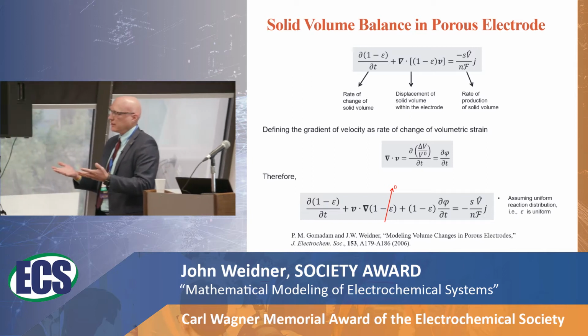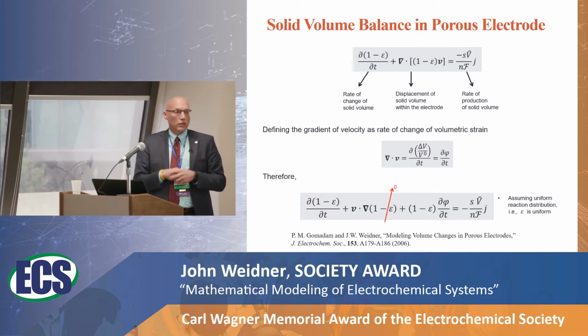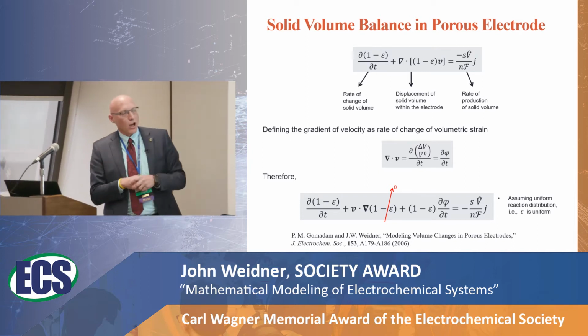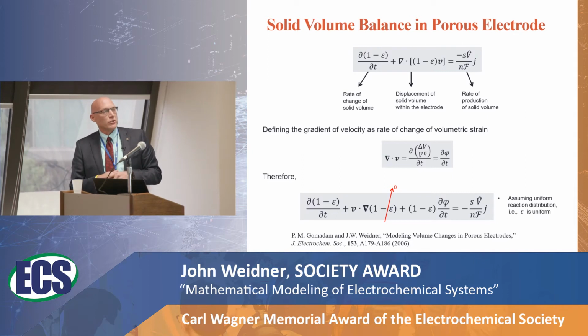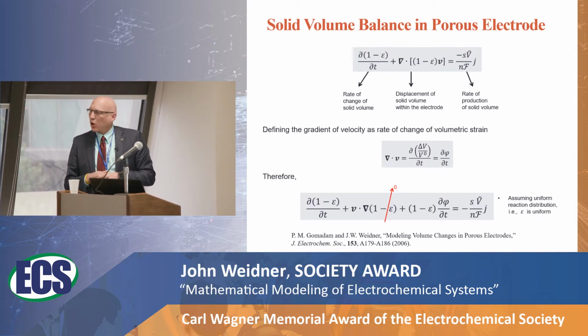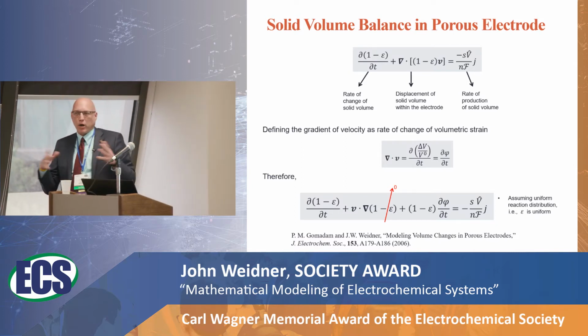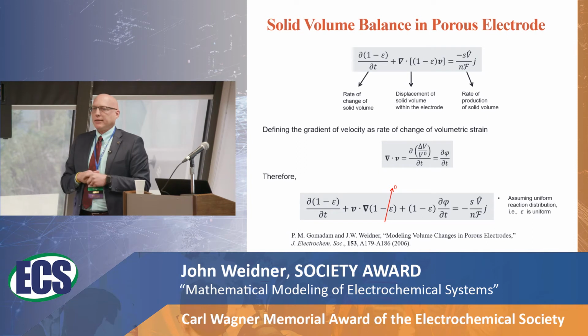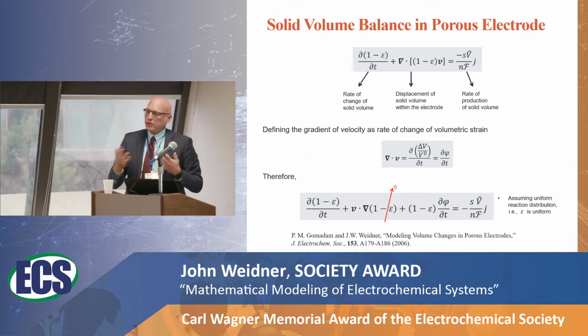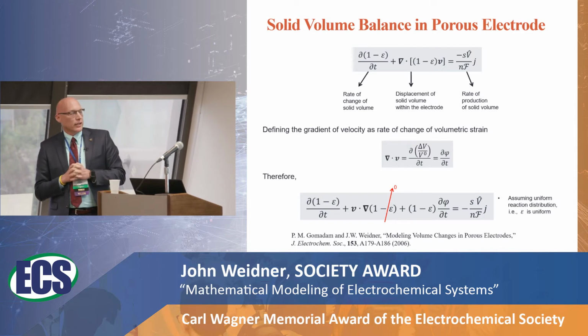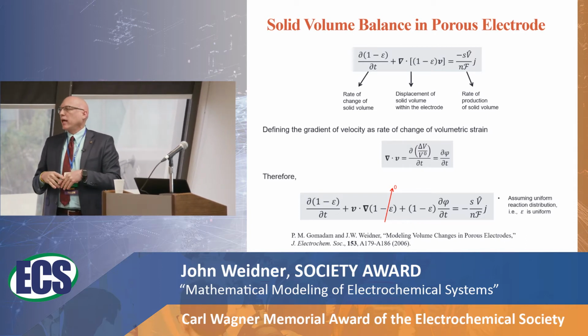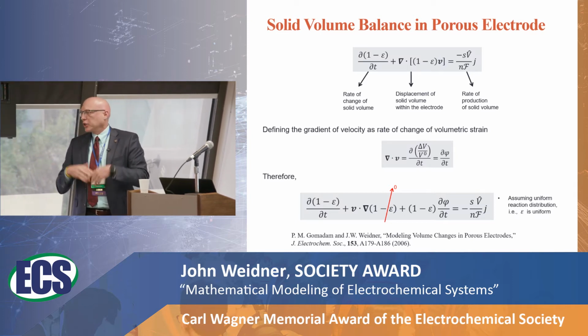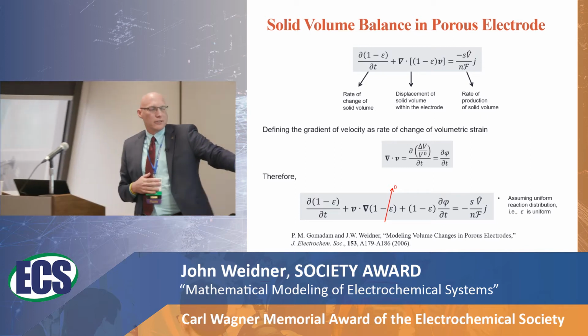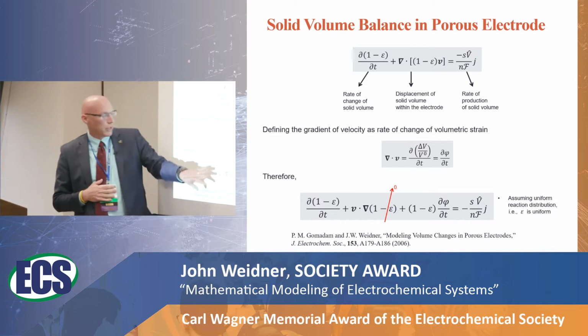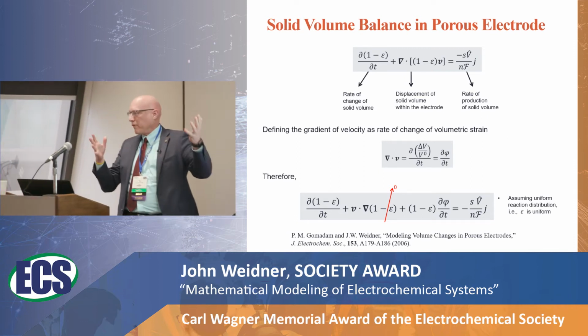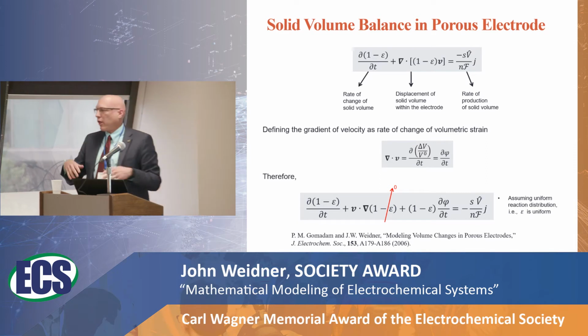done is add another unknown, but we didn't add another equation, right? We've added this, the volume expansion, the expansion of the electrode. We need another equation for that. So we couldn't figure out the relationship between the porosity and the volume change, so we just said, let's, and this was Partha Gomadam that started this, and he's currently at Medtronic doing battery modeling for medical devices. And he said, well, maybe we can't predict it, but let's just assume a value and split it between these two. Let's just say, oh, it's 50% volume change, 50% porosity change, 50% expansion, or 25%, 75%, or whatever number you wanted. We call that the G parameter.